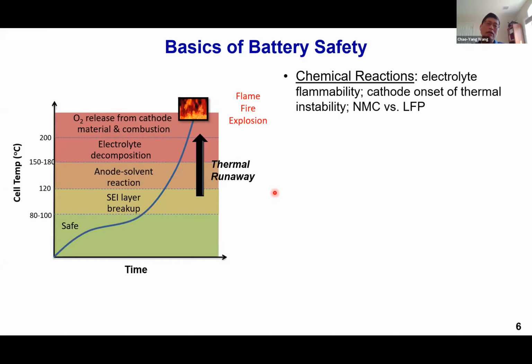But all those reactions described in this thermal runaway curve actually account for chemical reaction only. Such as, we often talk about electrolyte flammability and cathode onset of instability. And in this discussion, there's a lot of talk about NMC versus LFP, because the onset temperature for instability of NMC is around 200 to 250, whereas LFP is much higher, probably more than 500 degrees Celsius.